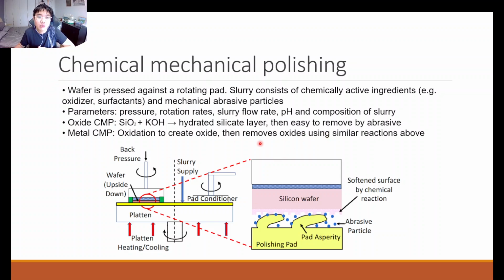So in this case, the wafer is actually pressed against a rotating pad, and this rotating pad has a certain asperity that allows it to engage with the wafer surface. At the same time, there's also a slurry that's applied to the wafer surface, and this slurry contains both chemicals that can chemically react with whatever you're polishing on your wafer surface, as well as abrasive particles.